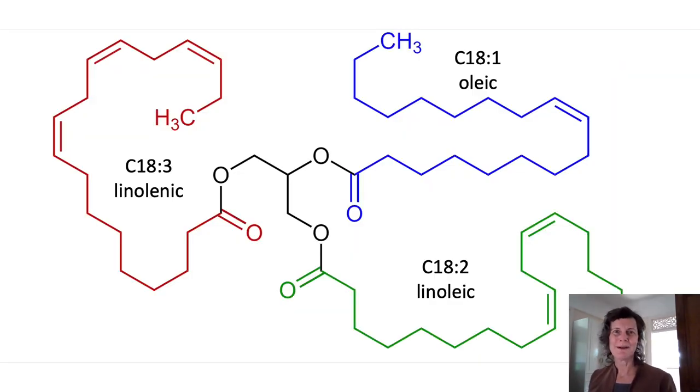First, it's helpful to be reminded of the triglyceride structures which form the basis of linseed oil. Constituent triglycerides are made up from a variety of fatty acids, most with chains of 18 carbons. The notional triglyceride molecule pictured here includes three different fatty acids, each with 18 carbons, and one, two, or three double bonds. The more double bonds, the greater the drying potential of the oil, as in the presence of air, the double bonds allow crosslinks to form, causing the oil to polymerise and dry.